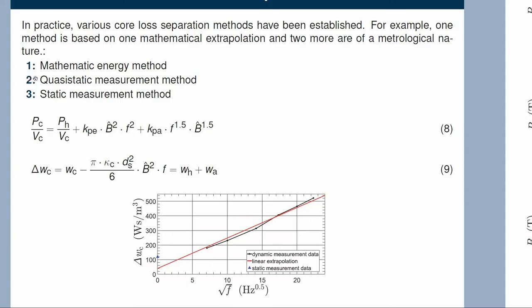The second method is a quasi-static measurement to bring dB/dt very close to zero by measuring at a very low frequency, perhaps one millihertz. When using a device under test in transformer no-load condition, there is noise on the secondary side because the signal is very small, making this a very difficult measurement. The third method is a static measurement using direct current, and this is the IEC standard for measuring the hysteresis properties of soft magnetic components — and my work is based on it.